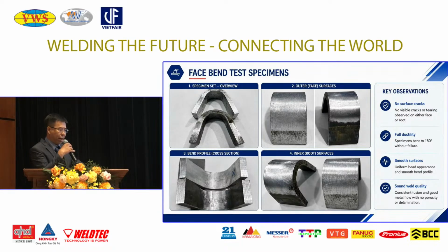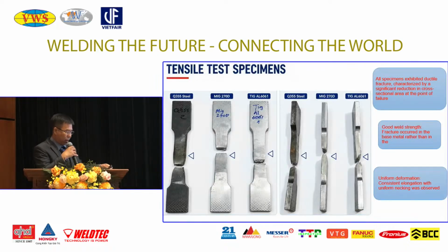This slide presents the bend test result. At the optimized welding parameters, the sample was tested for weld ductility and weld integrity under bending conditions. As shown here, the weld zone maintained integrity without failure during the bend test. This slide presents the tensile result of the weld zone. As shown here, the fracture occurs outside the weld zone, which indicates that the weld is stronger than the base metal.